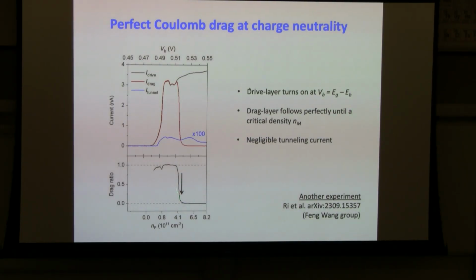Okay, I'll come back to this critical density later. The blue curve, let me just briefly mention, is actually the tunneling current multiplied by 100 times, so that if you really look at this scale, there's negligible tunneling in this setting. So we are in a pretty clean limit where we don't worry about artifacts from the measurement.